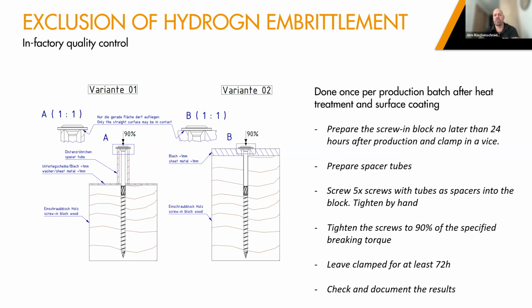So the block is clamped into a vise. We install the screw either as option 1 or option 2. Then 5 screws are tightened by hand to the 90% characteristic torque we define in the ETA. The screws are left in there for 72 hours, and then we check the screws. If the screws crack during this 72 hours, there is embrittlement happening in the screw. That means the whole lot will be blocked. If the screws stay tight and there is no relief, no cracking screws, then the screws are approved.